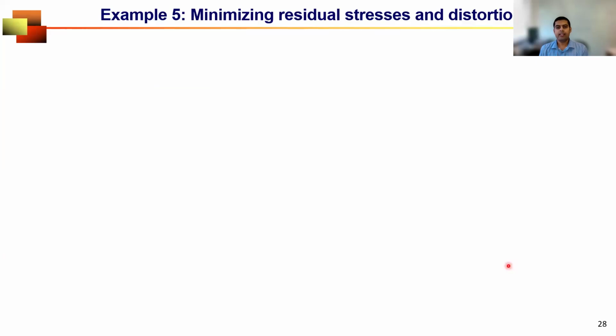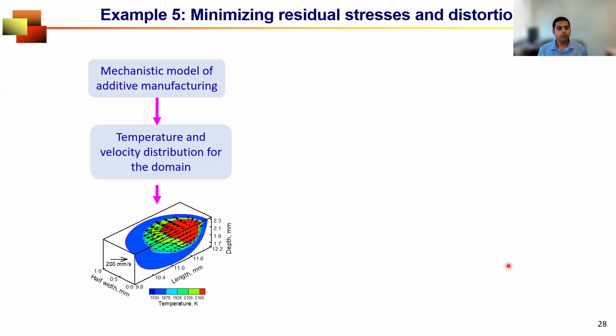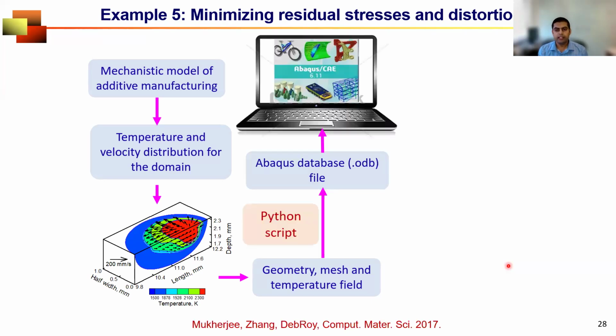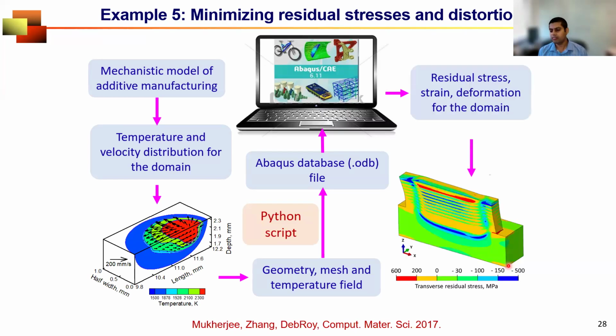Okay, the next example is minimizing residual stress and distortion. So I think probably residual stress and distortion are the two most important problems in additive manufacturing, because in additive manufacturing, we try to print dimensionally accurate complex parts, and we don't want our part to distort. So what we did, we started from temperature field calculation, and then took that temperature field calculation along with the geometry and mesh, and took that to a mechanical model, a finite element based mechanical model, and calculated residual stress and distortion.